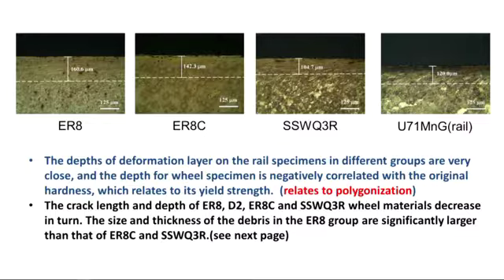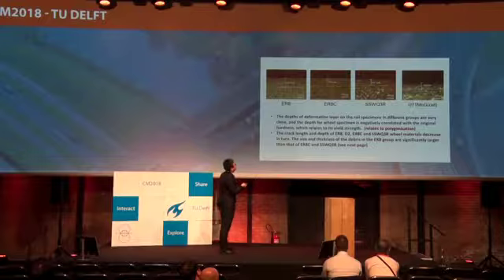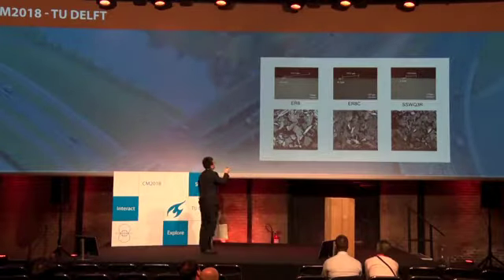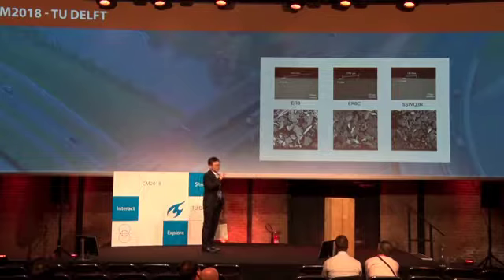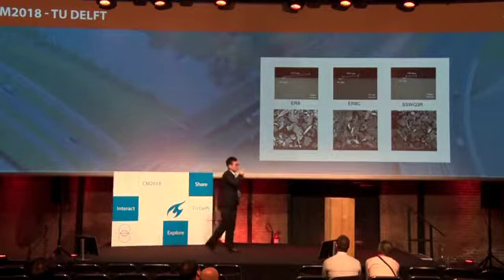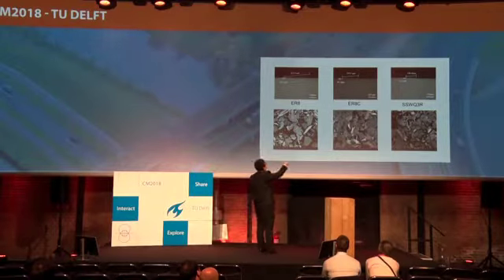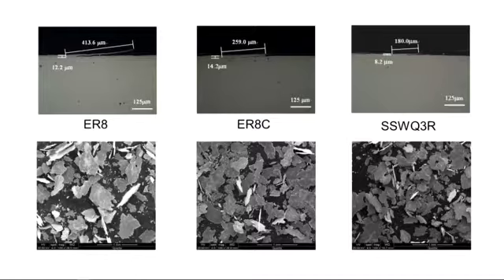And this is, oh, sorry, this is the past. These are the crack lengths, because after the test, we observed cracks on the surface of the lamella. And when the hardness increases, the cracks tend to be shorter and shallower.